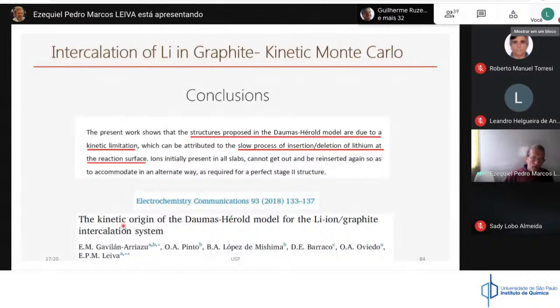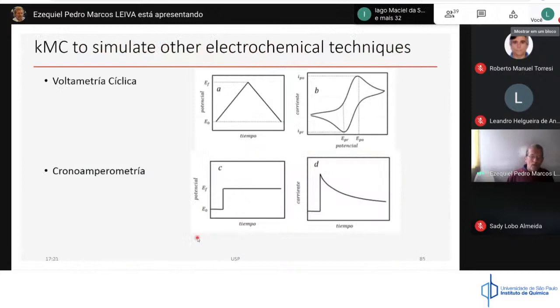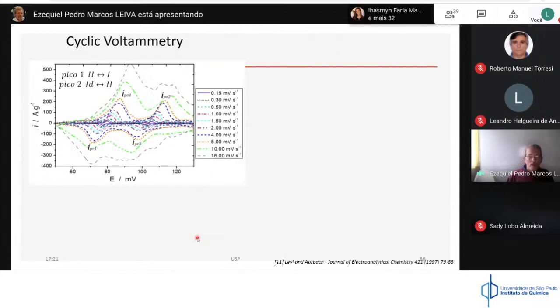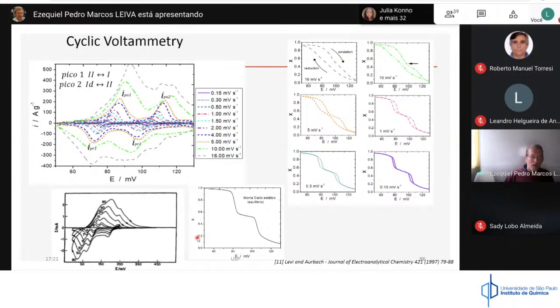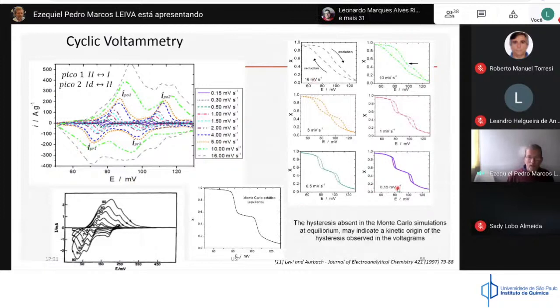We published a work on that. We were surprised because at the beginning we thought the results were wrong, and actually what we found is a very, very interesting kinetic phenomenon. From this kinetic Monte Carlo simulation, you can also make cyclic voltammetry, or get other techniques. This is, for instance, cyclic voltammetry. You can run cyclic voltammetry at different rates, and depending on the rate, you can study the hysteresis in the isotherm. You can very nicely study kinetic effects by these kinetic Monte Carlo simulations.